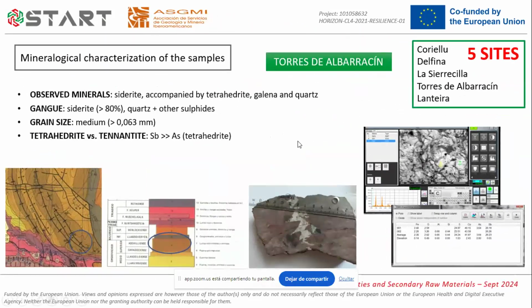In Torres de Albarracín, it has been observed that the main minerals present in the samples are siderite, accompanied by tetrahedrite, galena, and quartz. The main gangue here is siderite, which accounts for more than 80% of the whole sample, plus quartz and other sulfides that are mainly galena. The grain size here is medium, and antimony content is higher than arsenic content, so here we have also tetrahedrite as the main mineral. This site has also been selected for the study.